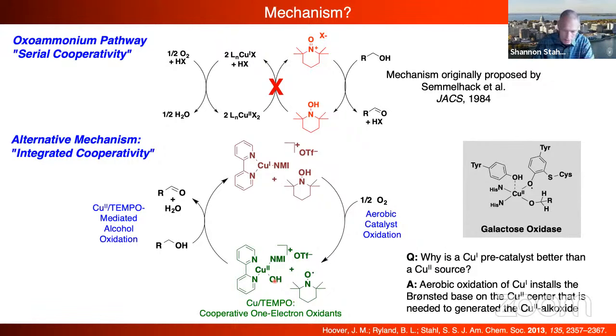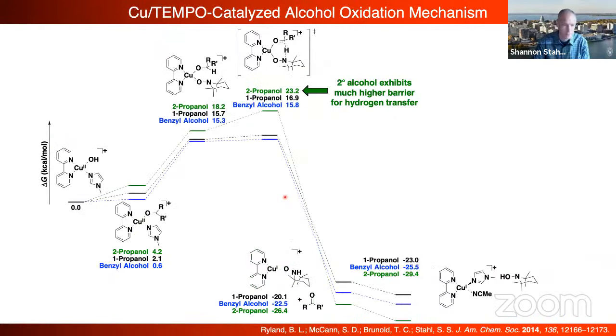This is not unique to this system. We've seen it in a number of other copper systems where if you start with copper-1 and reduce oxygen as the initial step of the reaction, the installation of base into the copper coordination sphere actually engages substrate effectively and turns over the catalyst very, very well. The main point here, though, is the joint cooperation of 2 1-electron oxidants bypassing the 2-electron redox couple hydroxylamine to oxoammonium. Let me just briefly highlight the mechanism of this reaction.